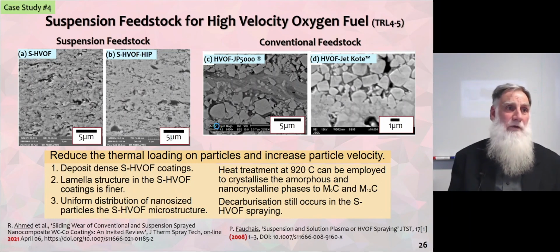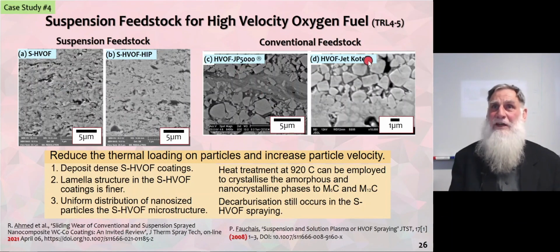A more recent review by Ahmed et al., this came out just a few weeks ago in the Journal of Thermal Spray Technology, looked at the microstructures of suspension feedstock fed into a high-velocity oxygen fuel torch, compared to conventional feedstock. The micrometer marks are approximately the same, but you're able to see that the suspension feedstock gave rise to a much finer microstructure where you can actually see some of the carbide particles, whereas they are very obvious with regards to the JP5000 and the Jet Kote high velocity oxygen fuel processes.